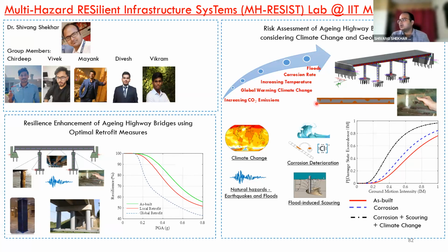Okay. So this is my reinforcement. You can see that these pits are forming randomly across the length of the rebar. To model this, we have gone through the experimental test results done by certain researchers. They took 100 mm reinforcement, did the accelerated corrosion test, and then tried to find the pitting factor at different locations. Based on this, they give a distribution of the pitting factor. That distribution is a Gumbel distribution with a mean parameter and a shape parameter.